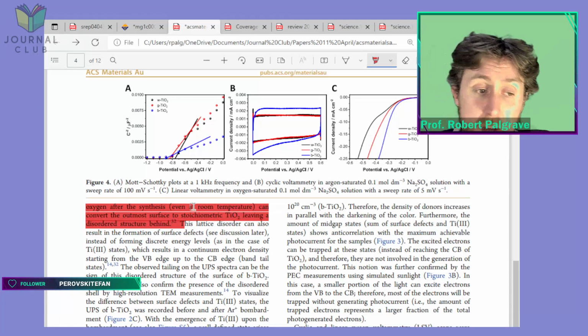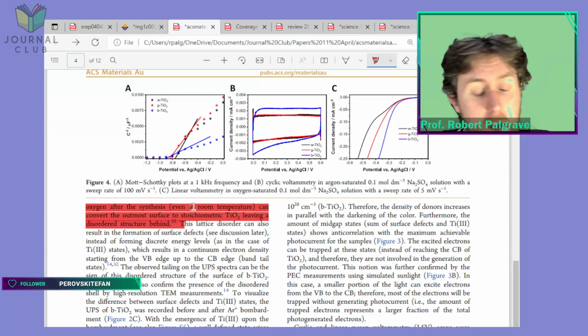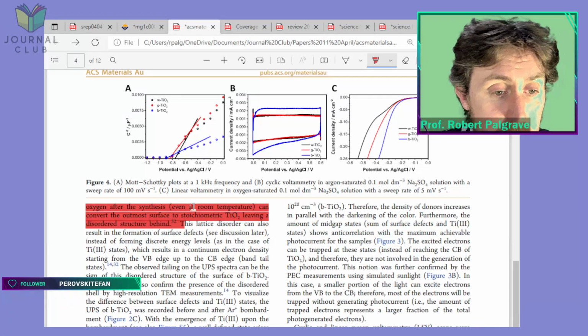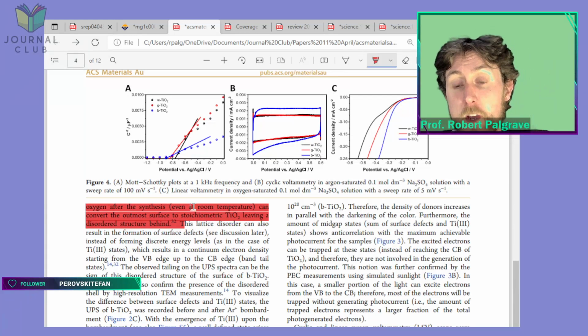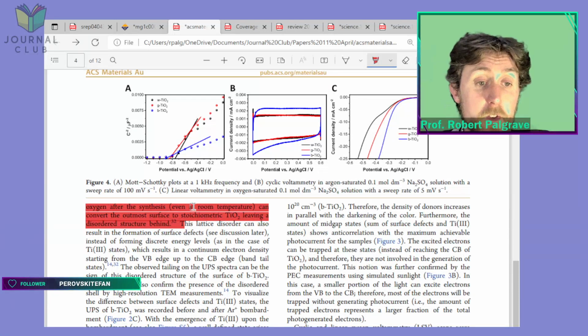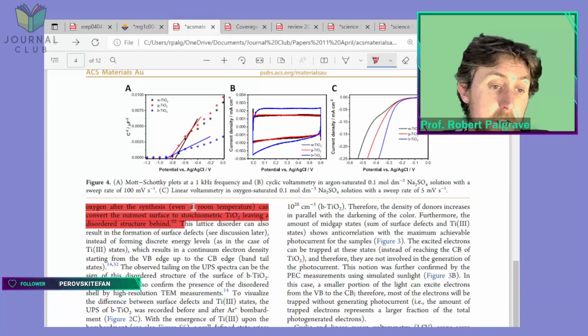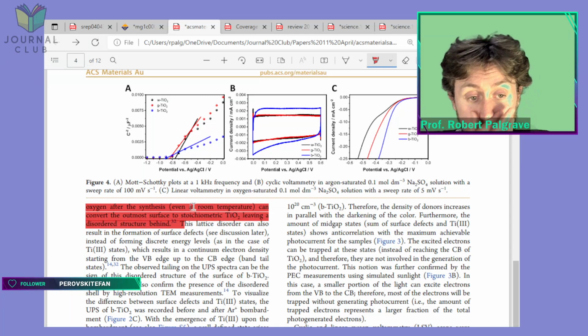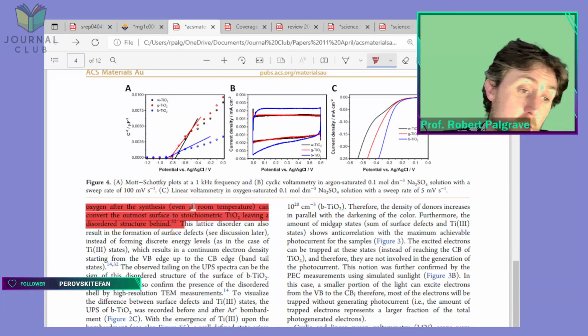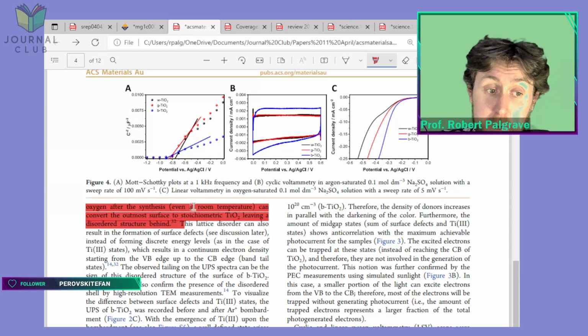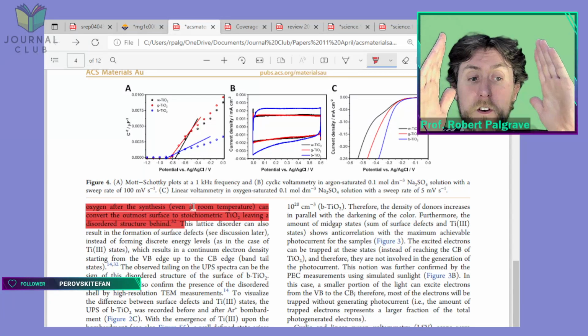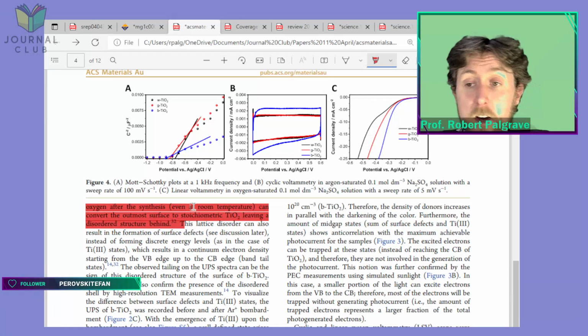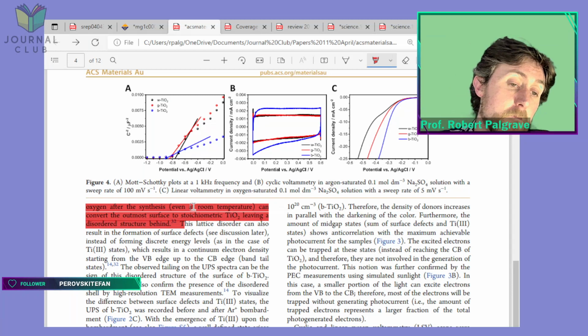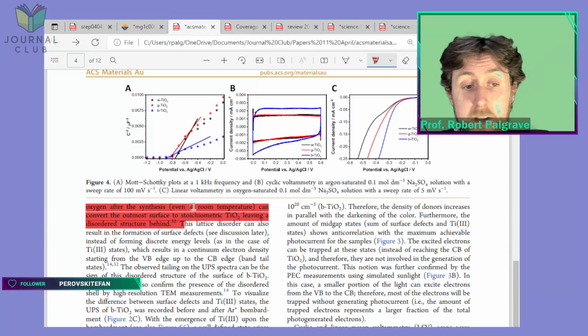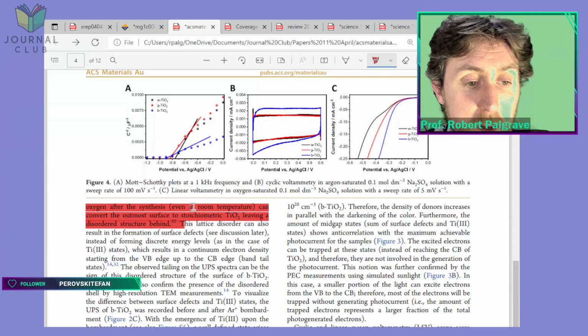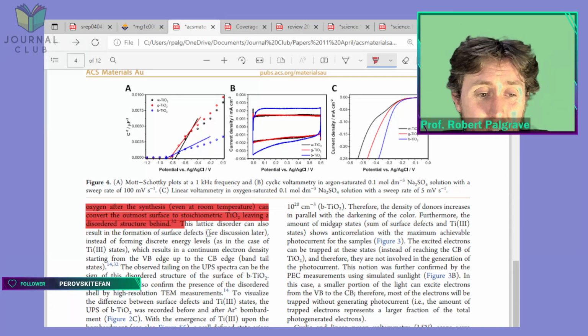You could argue, well, maybe it's got a higher surface area, maybe the surface is more reactive for some reason. Yeah, maybe it is. Maybe it's got hydrogen in there that somehow helps. Maybe it is. The obvious experiment you could do, if you wanted to test this, is do the whole thing in a glove box. So don't expose it to oxygen, don't expose it to air after the synthesis. Do the experiment in a glove box, or transfer it after the experiment into a glove box without exposure to air. You could put some seals on the end of the tube furnace, probably possible to do that. Get it in a glove box, then load it into the XPS from the glove box, see whether you see any Ti3+. That would kind of test that hypothesis, I think. But yeah, I'm a little skeptical about it.